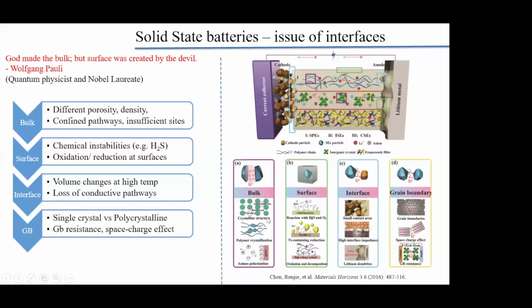For example, if you use polymer, then they should have the right kind of porosity, density, crystalline structure. At the surface, there should not be any inadvertent oxidation, reduction, or other chemical reactions. At the surface interface, you need to have the right kind of contact. And then you have something called grain boundary. A single crystal is better than polycrystalline, because the more boundaries you have, tougher it gets. And that's why single crystal is better.